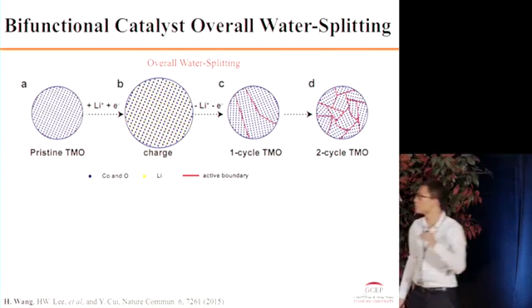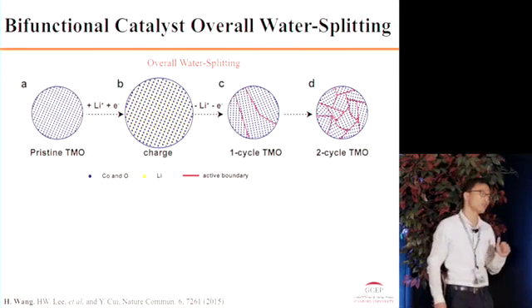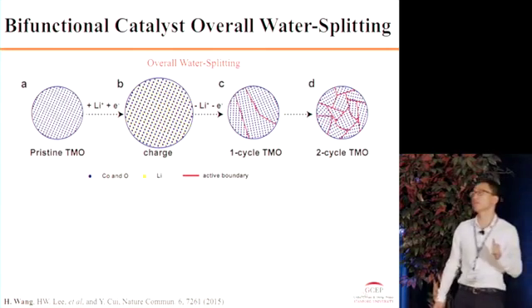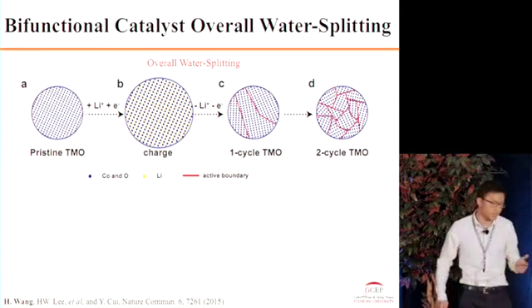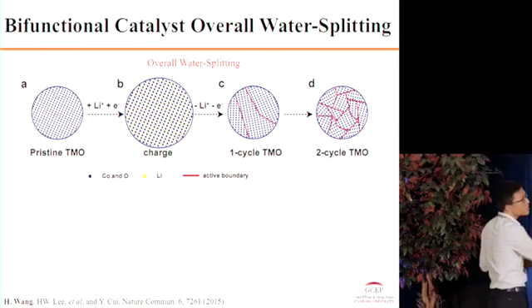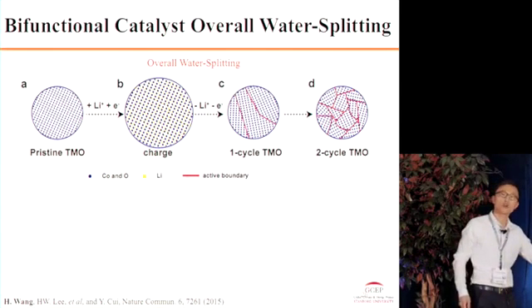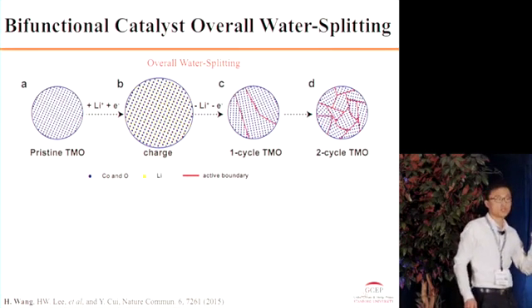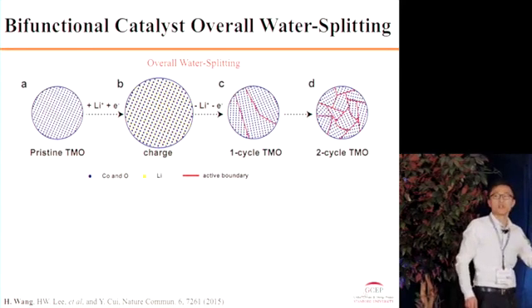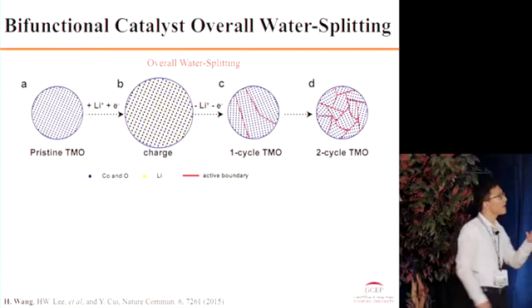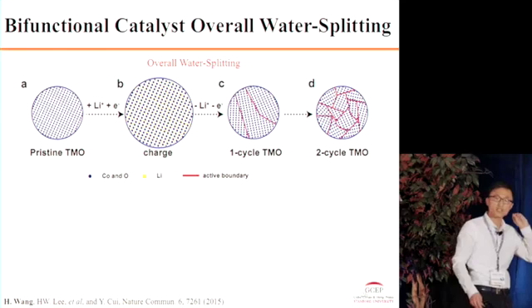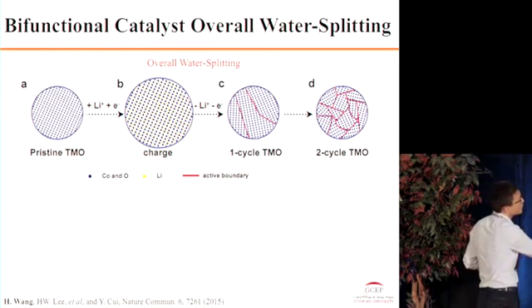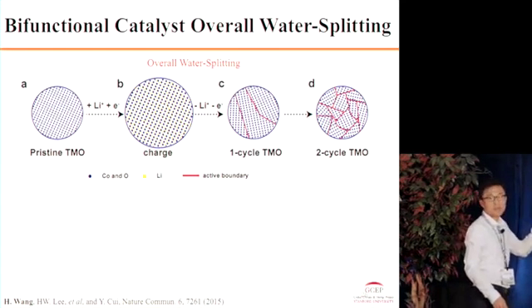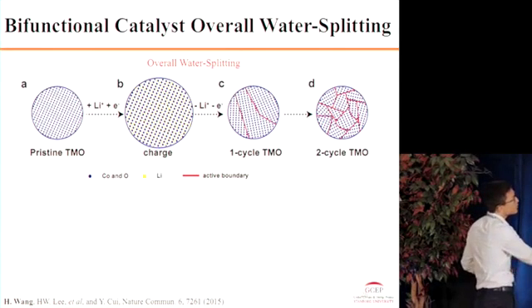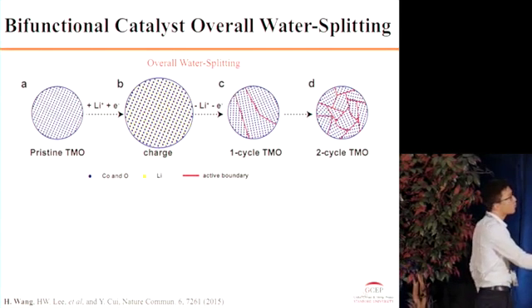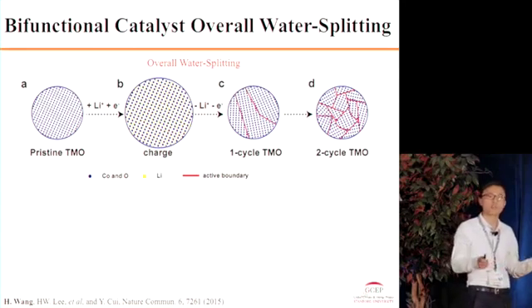So the way we want to increase the catalytic activity of transition metal oxide is also inspired by the lithium-ion battery studies in our group. Transition metal oxide is also a traditional lithium-ion anode material. And the studies in this community found that after several cycles of lithium charge and discharge, that is, lithium goes into the transition metal oxide and comes out, the structure of the particle will be significantly changed after several cycles.